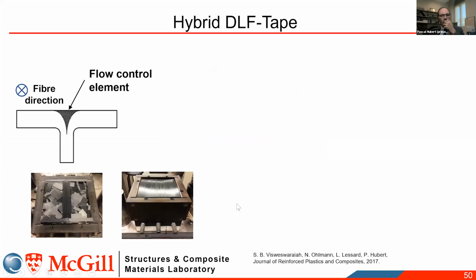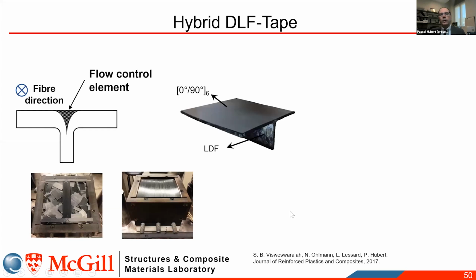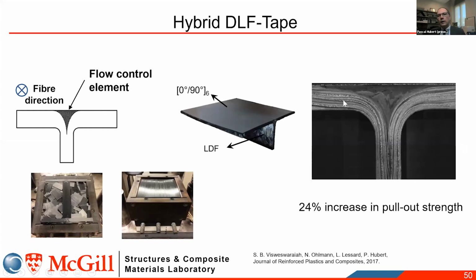Another very interesting application of these hybrids is that you can design by placing continuous fibers in strategic places in the mold. Like here in this case, I'm showing a kind of prism laminate that we place right at the base of that rib. So then when the fibers are flowing in that rib, they will be guided by this flow control element. And what you end up with is, on the right, you'll see clearly that the strands or the platelets have really followed nicely the radius in that rib. And that led to a significant increase in resistance of that part.